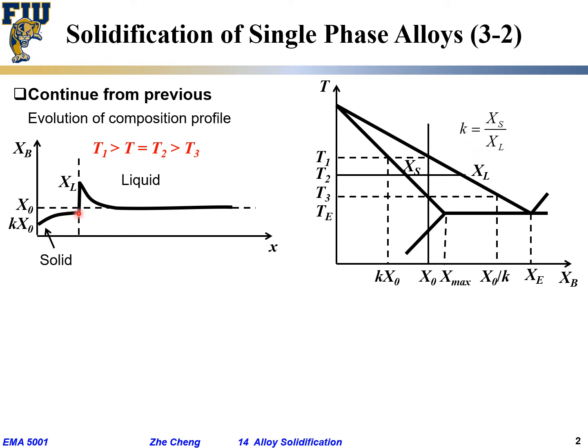And then deep within the liquid, we said it's a diffusion phenomenon. Deep within the liquid, for simplicity we assume the liquid composition is whatever is its initial liquid composition, which is x0. So deep within the liquid I'm still at x0. At the interface I'm at xl, which is higher than x0. So the concentration profile would look like: it rises at the interface, but deep within the liquid it goes down again. Across the interface into the solid.